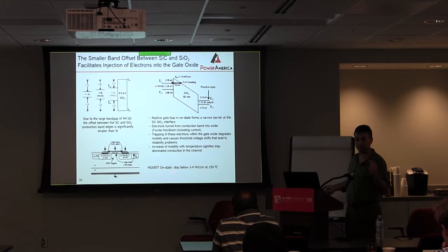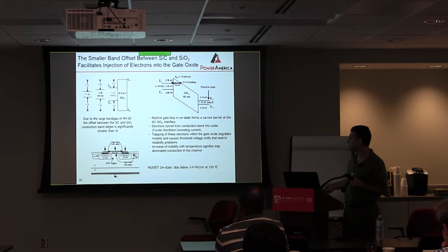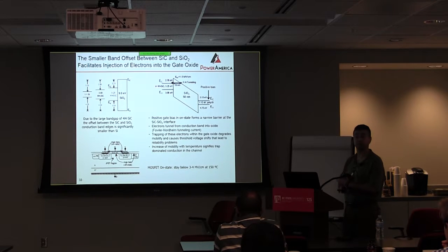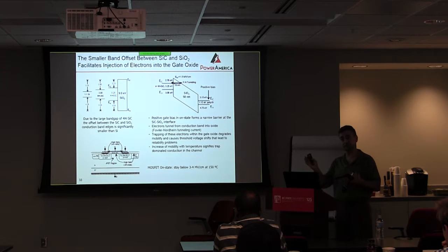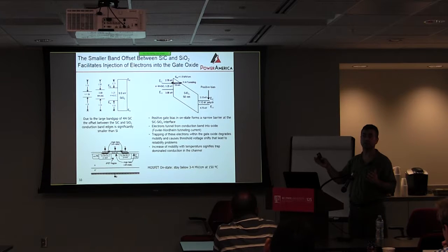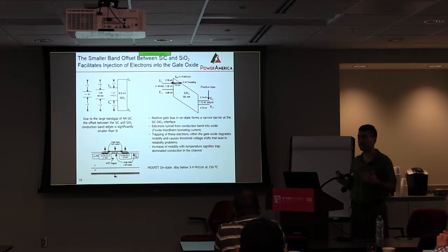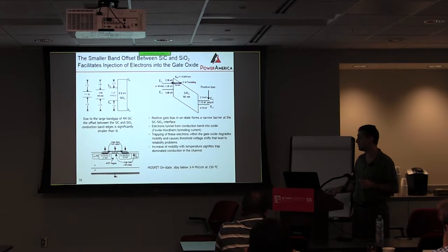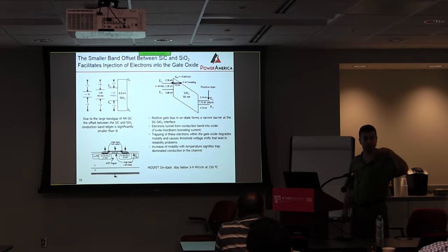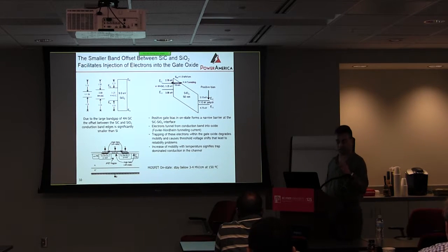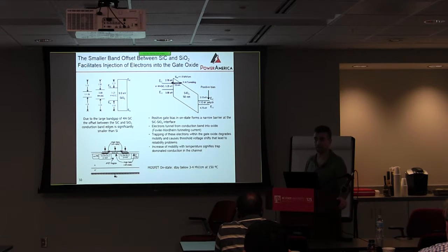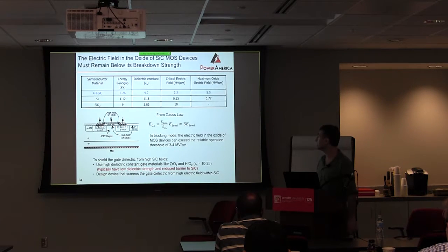So what you need to do, when you operate a silicon carbide MOSFET in the on state, is stay below 3 to 4 megavolts per centimeter at 150 C, and that also kind of sets a limit to how high in temperature the MOSFET can operate with the gate oxides that we have today, which is basically a nice SiO2 treated in a nitrous type of environment to increase the mobility, to make it higher quality. You're limited to about 175 degrees C, maybe 200. And that's why if you look into any spec sheets of MOSFETs sold commercially, the temperature of operation is about 175. That's what they provide.